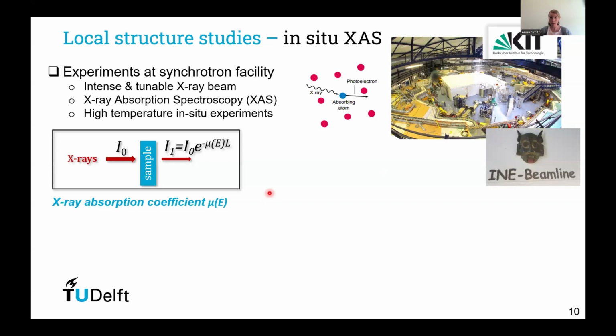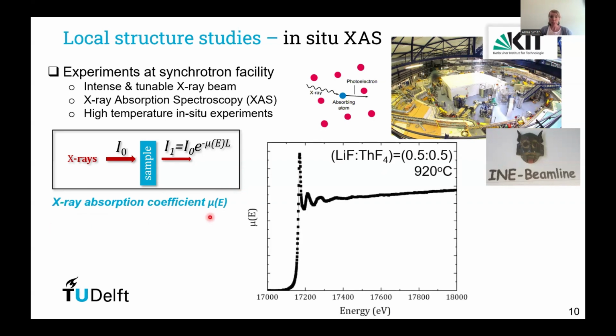So we have built in Delft a furnace setup to be able to heat up our molten salt systems at high temperatures, and we bring this furnace to a synchrotron facility in Germany, where we measure then the X-ray absorption coefficient of a certain sample. So when we shoot some X-rays to a sample, we can measure the intensity before the sample and after the sample, and we, in this way, measure the X-ray absorption coefficient as a function of energy.